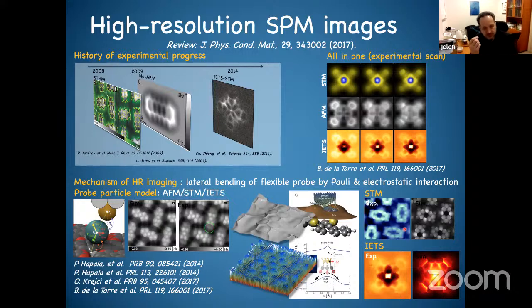So very briefly, what is behind this contrast? We call this method the probe-particle method. It means that the CO is like a particle hanging freely on the apex. When you approach close to the surface, the CO starts to bend, and this bending introduces an enhancement of the contrast. There are two effects. The first: if you have a metallic tip and you approach the molecule, typically you pick up the molecule from the surface, and that's it. But when you decorate the tip with a CO molecule, you passivate the tip chemically. The CO is not very reactive, so now you can go very close to the molecule, to the repulsive regime, and see the bending of the CO in stable conditions, which enhances the contrast.